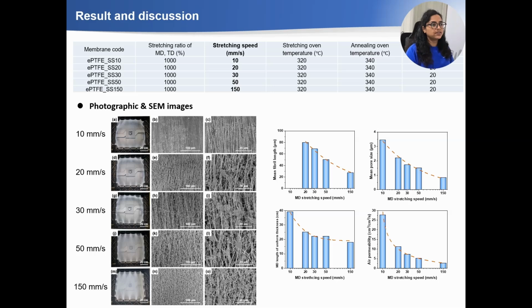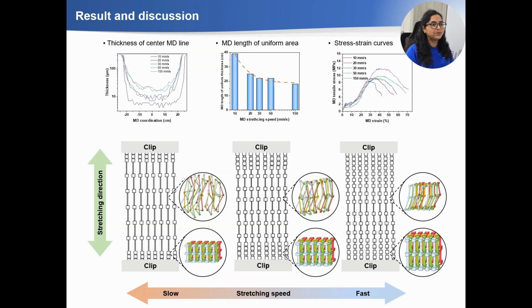Also we check the stretching speed, SS, as a stretching parameter. We change the stretching speed from 10 to 150 mm per second, and we conclude that the stretching speed has a notably great influence on the quality of the PTFE membrane.